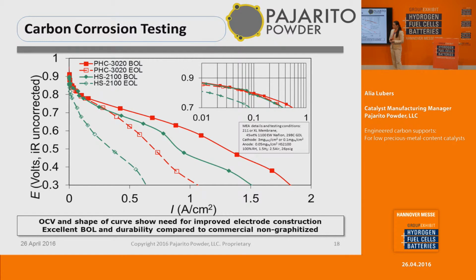Some results of that test comparing our support materials that have been platinized with a high-spec platinum on carbon, which is the commercial catalyst available today. We can see that our beginning of life kinetics are relatively similar to each other. However, after carbon corrosion, our support maintains similar kinetic activity, where for our high-spec platinum on carbon, we see some loss in activity. For our carbon support, we have some loss of some transport properties, but we see even more for the high-spec platinum on carbon.